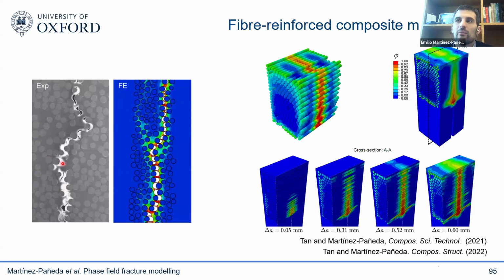But what I find powerful about this, not only the ability to simulate experiments quite nicely, but is the ability to run 3D simulations. Because when you run 3D simulations, you can capture the fiber bridging phenomena. So you can capture the R-curves, you can capture how, as the crack propagates, the fibers are naturally bridging the crack. And this is very powerful because in all the other models that I have seen before, the toughening due to fiber bridging is an input to the model. So you need to run an experiment, you calibrate that, and you put it into your model. Here, we predict the fiber toughening as an output of the model. So we can try what happens if you change the shape of the fibers, what happens if you change the strength or the toughness of the fibers, and so on and so forth.